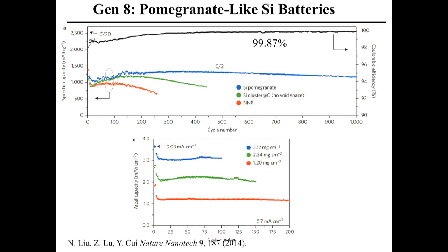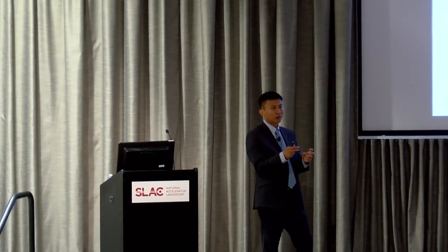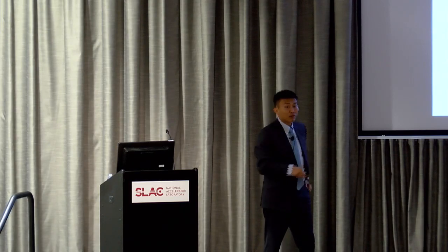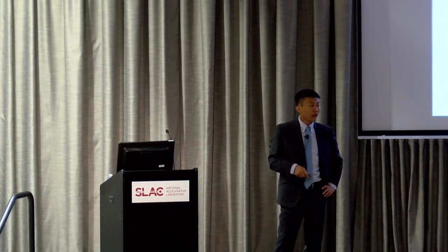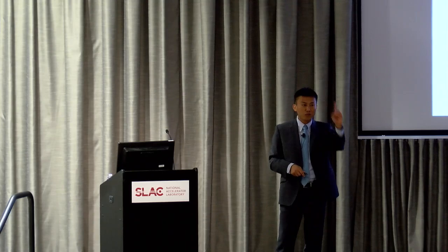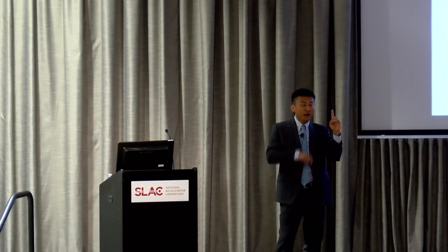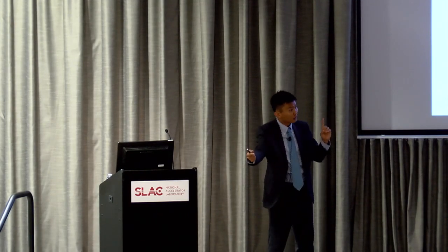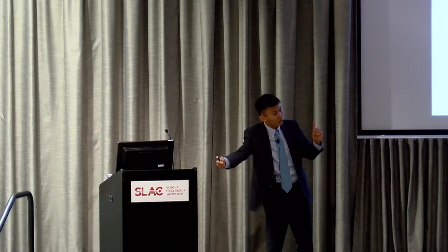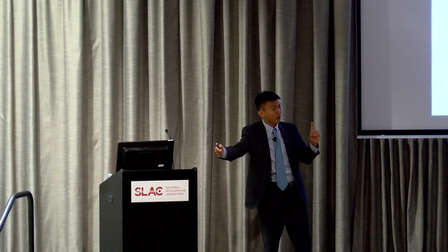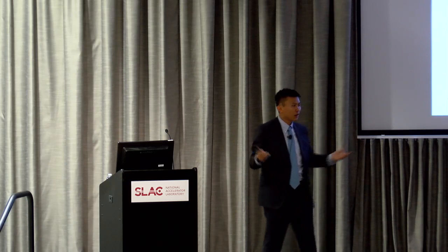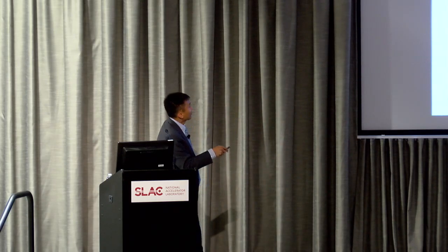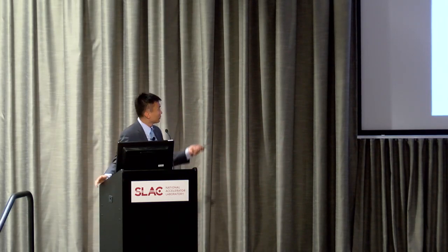99.87, you want 99.9. What does this mean? This tells you if you lose 2 electrons every time, there has got to be a side chemical reaction happening right there. If it's 98%, you will calculate right away. Capacity is 1. Next cycle is 98. Next cycle is 98 times 98, 98%. And after 100 cycles, you don't have capacity anymore, right? So you need this high Coulombic efficiency.